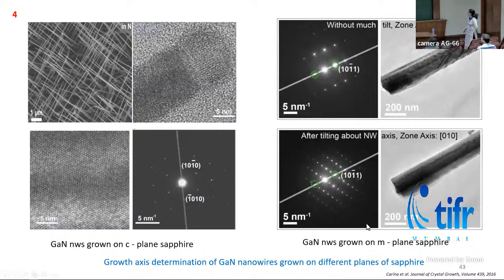This is an example of imaging gallium nitride nanowires. Semiconductor nanowires are very important in applications such as electronics and photonics. This is a SEM image of gallium nitride nanowires. We have grown these nanowires on different planes of sapphire and studied them. When we check the nanowires, we check the crystallinity of the wires. Looking at the high resolution TEM image, we can see that these wires are defect free.